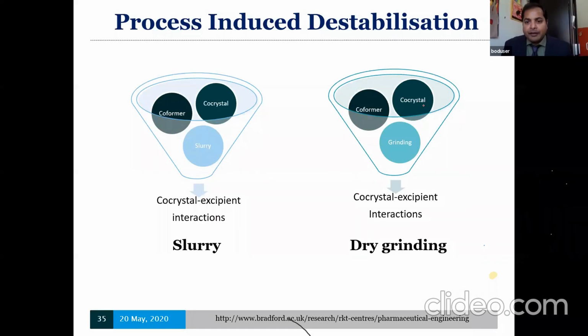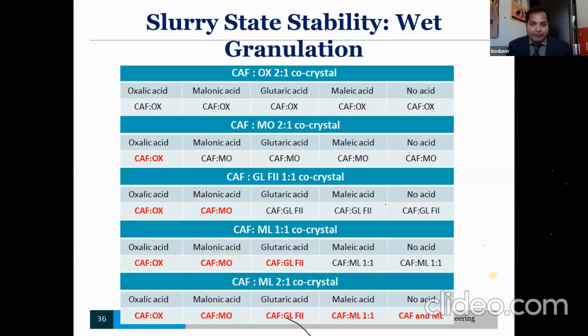And similarly, we have also extended such studies with dry grinding. We have taken the co-crystal and co-former, made a grinding, and seen what happened to the system. This slide is slightly busy. I would like to draw your attention to the caffeine oxalic acid co-crystal: if you take it and mix it with malonic acid, glutaric acid, or maleic acid, nothing has impacted it in any way. So the caffeine oxalic acid co-crystal was completely stable. Adding any of these additives has not altered the crystal structure, or broken it down or dissociated it. Whereas if you look at this particular example, I will draw your attention to it.